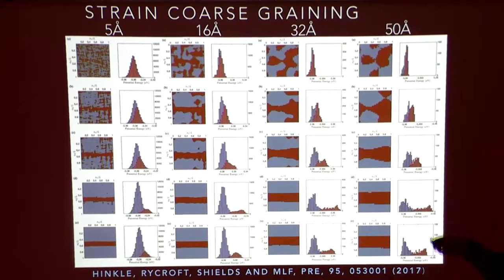In this case, we used a Gaussian windowing function to coarse grain the atomistic simulation. The first thing I'm showing is if we coarse grain at different length scales and look at different applied strains, the strain is going up as we go down. So here this is unstrained, fully strained, and then we look at histograms of the material that's over the nominally imposed strain and under it.